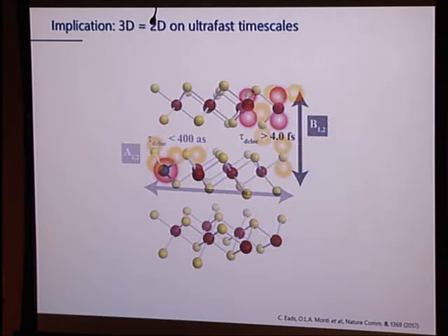So what this is saying is that we have in plane very short lifetimes, out of plane relatively long lifetimes, and so dynamically on short timescales, even a bulk material that is layered already behaves as a purely two-dimensional material. So on short timescales, I don't need to go through the trouble of preparing monolayers and so on. On short timescales, I have intrinsically a 2D material.